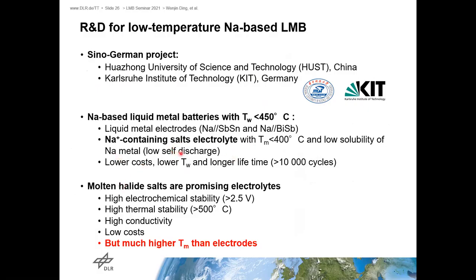And we also hope this new liquid metal battery has similar excellent performance as the conventional batteries and also the lithium-based batteries. Molten halide salts are promising electrolytes for such a battery, because they have high electrochemical stability, high thermal stability, and high conductivity, but low cost. But the problem is that halide salts usually have high melting temperatures, especially for the sodium-based liquid battery.